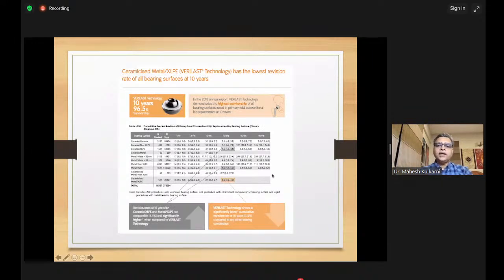If you see the failure rates at 10 years, this is a very busy slide, but just follow these 3 lines. Ceramic on highly cross-linked polythene, 4.5% revision rate at 10 years. Metal on highly cross-linked polythene, 4.5, and oxidized zirconium is 3.5 at 10 years. So for survivorship in the first decade following a hip replacement, metal and ceramic on highly cross-linked polythene have the same result, but oxidized zirconium has shown a slightly better result in the first decade. We still have to see the second decade because we are expecting these younger patients to last much longer.